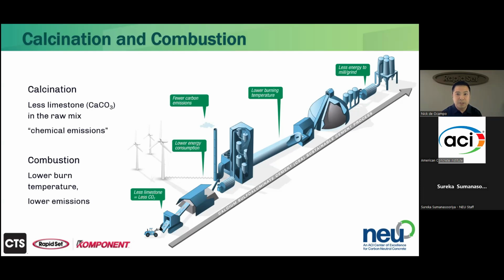In the previous slide, we talked about the chemical emissions. That's from the separation of the calcium from carbon and oxygen in limestone, CaCO3. So the calcium has to be freed up so it can bond with silicates in a Portland cement kiln, and sulfates and aluminates in a CSA cement kiln, to create CSA or to create the calcium silicates in Portland. And then the rest, the carbon and the oxygen, form CO2, and those are emitted. So because CSA cements use less limestone in the raw mix, you get significantly less chemical emissions.